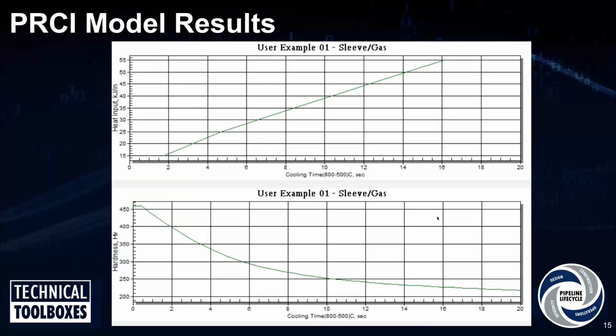So typically from an in-service welding situation, from a cracking perspective, what you have is a minimum welding heat input. So as long as you weld above the minimum welding heat input, you know that that weld will have a less hard microstructure. And on the flip side, from a burn through perspective, if you have a risk of burning through, how you mitigate that risk is applying a maximum welding heat input. So then in those situations, the welder has to be able to maintain his weld above a minimum value and then below a maximum value.